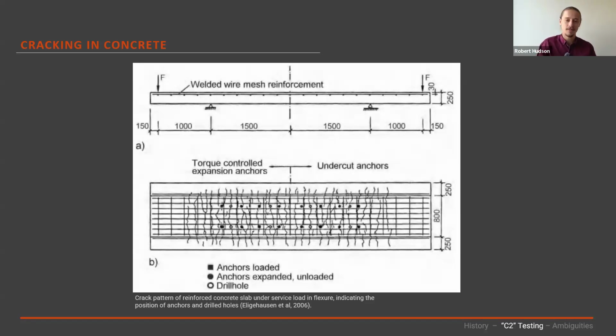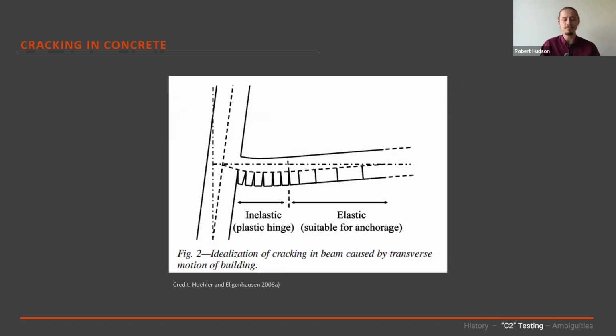And this makes a lot of sense. We have a reasonably homogeneous material. If we put an anchor into it, it acts as a stress raiser. And when we start getting cracking in these concrete units, which we do even under just service loads, but definitely under design level loading, because we have a stress raiser there, there's a very good chance that crack occurs where the anchor is. So the baseline assumption is that if we're putting an anchor into concrete or reinforced concrete, when cracking occurs, it is going to happen where that anchor is. And that's a pretty reasonable assumption in my mind.